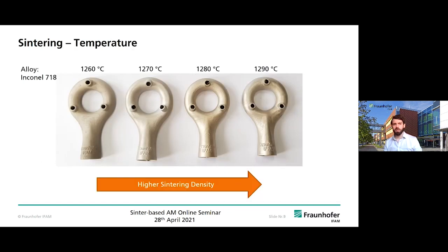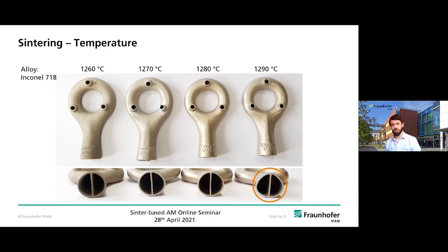Some impression of some Inconel 718 results we did in the past: when you sinter Inconel 718 in the solid state, as you can see on the left hand side, you get parts that have quite good density, but most of the time you need some higher sintering density, so you increase the temperature. And how much liquid phase is possible and appropriate to maintain the shape? There we can see that with increasing temperature, the density increases, but as well the distortion.